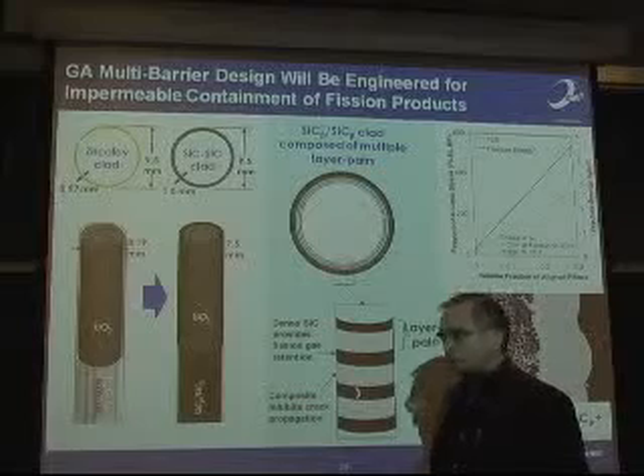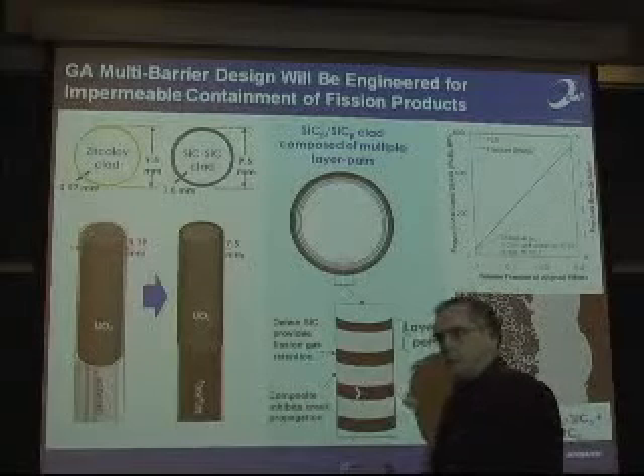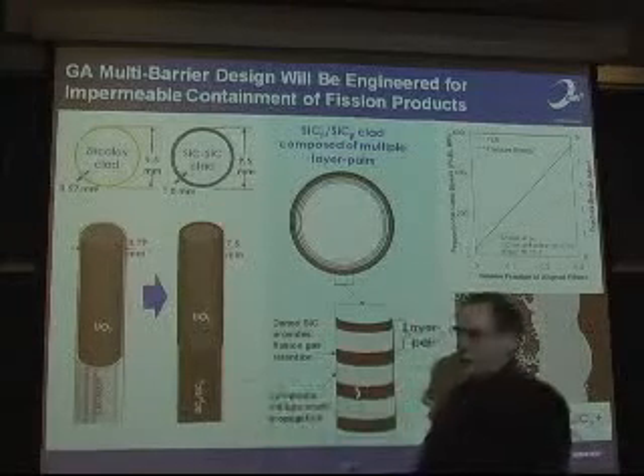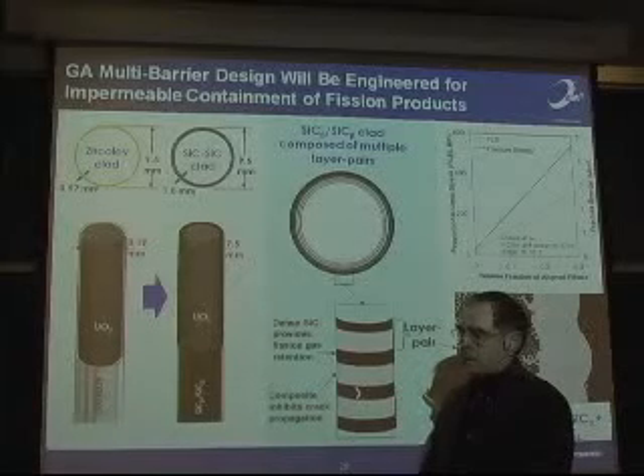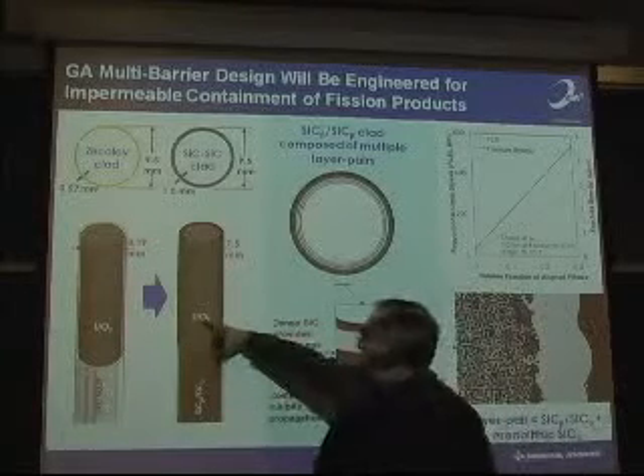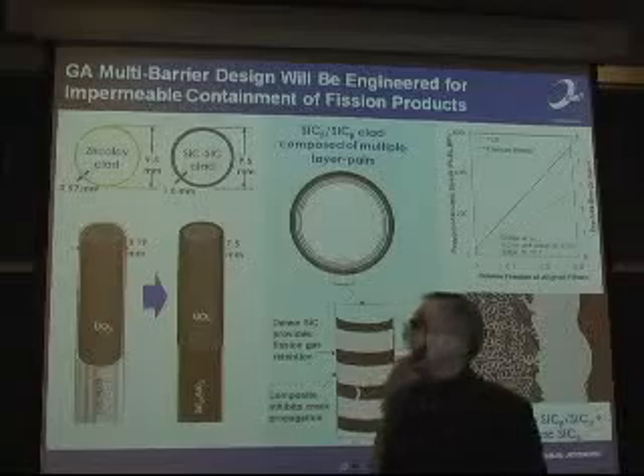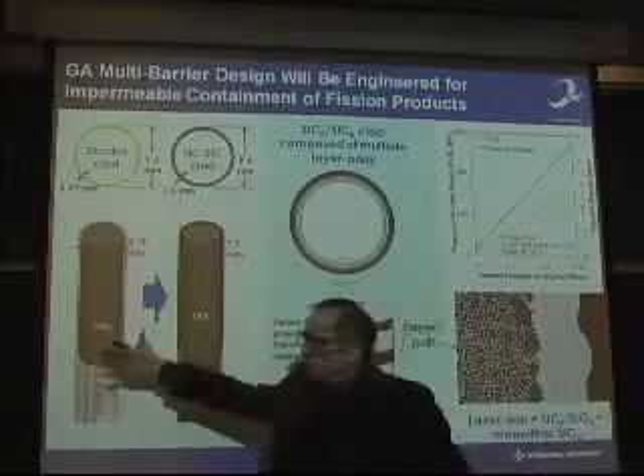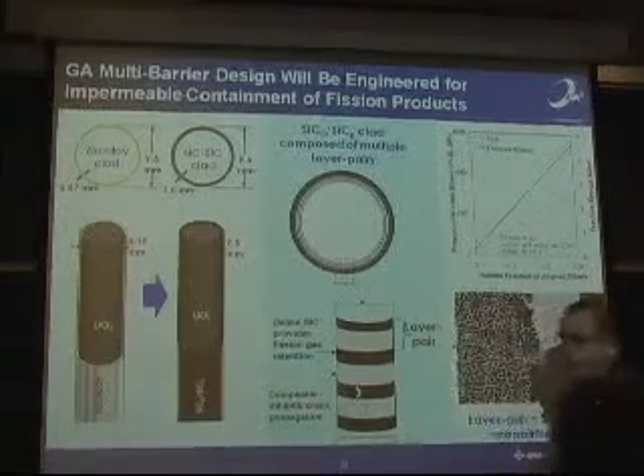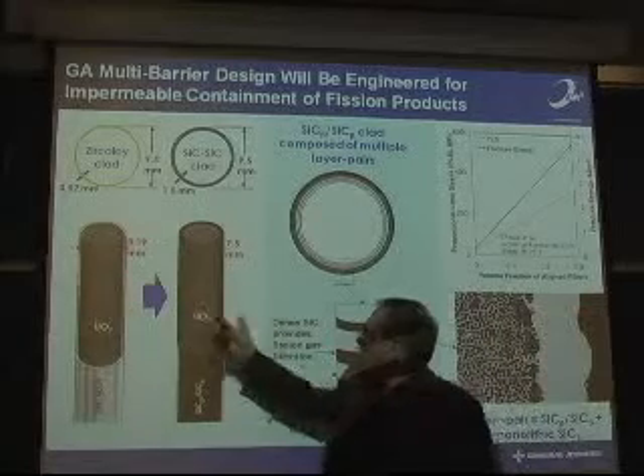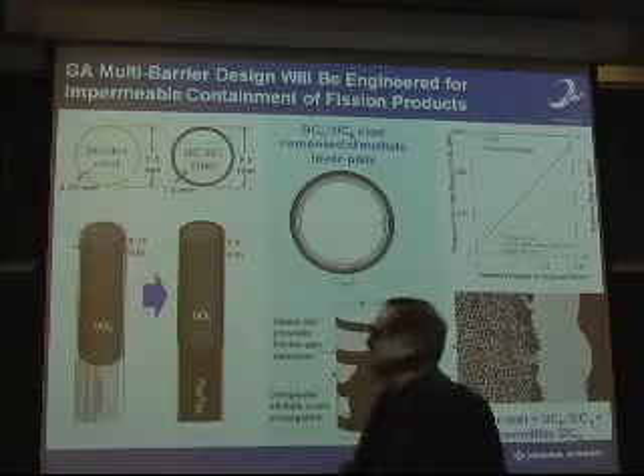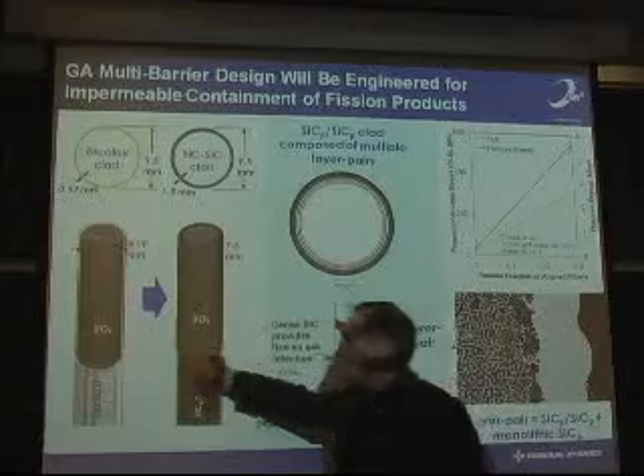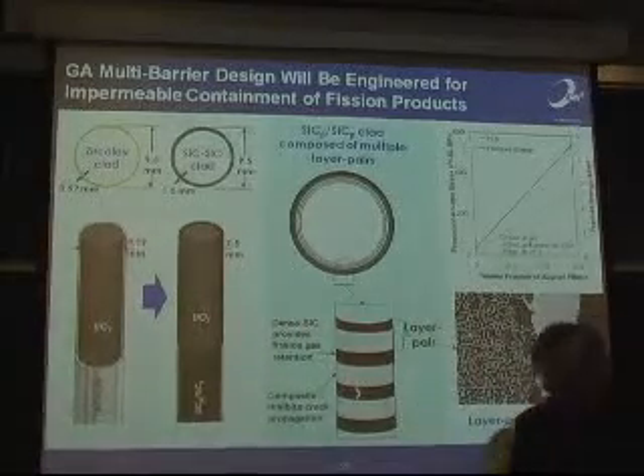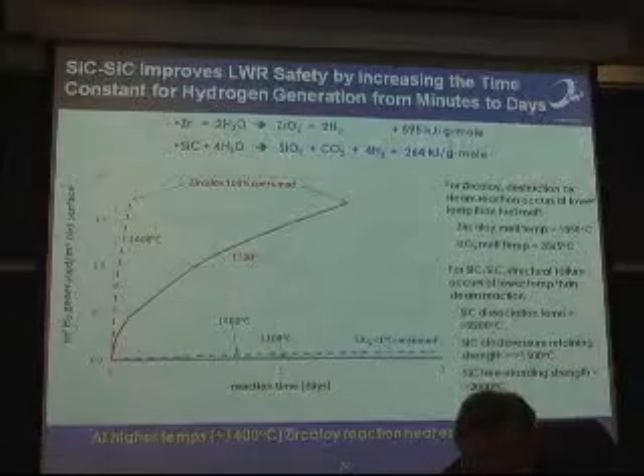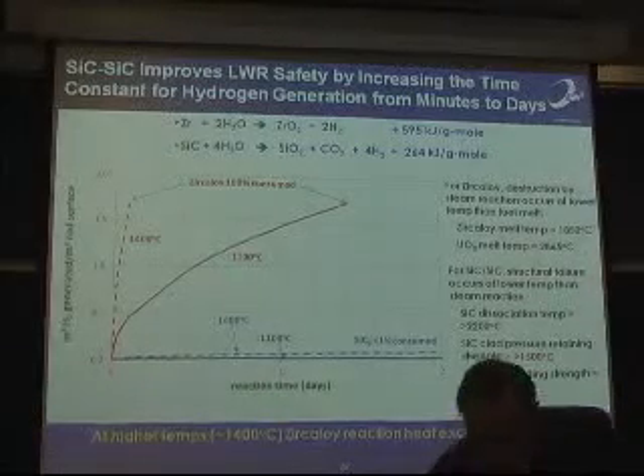And so you gain a little reactivity by going to the silicon carbide, and you only have to increase the enrichment here by about 0.6% in order to get the same lifetime as the UO2. And since you're buying 20% less, the fuel cost for this will actually be lower than this here. So I'm not going to go through all of this because the time is getting late.